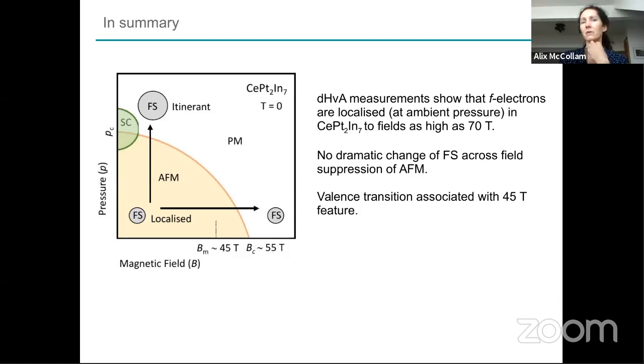The total volume of the Fermi surface shouldn't change, right? The number of carriers shouldn't really change unless you're taking an f-electron in or out, and then the Fermi surface can get larger or smaller. The effective mass is given by the temperature dependence of the quantum oscillations. So in a large Fermi surface, you expect that the f-electron is involved in the Fermi surface, is somehow hybridized into the conduction band. So then you would expect an enhancement in the density of states, enhancement of the mass, and of all the quantities that I talked about earlier. So it's not that the effective mass affects the volume, but when the f-electron is absorbed or somehow pulled into the Fermi surface, you expect the mass to increase. So that's the relationship between the mass and the Fermi surface volume in this context. Does that answer your question, maybe? If it doesn't, you can write again and I'll try to make a better attempt.